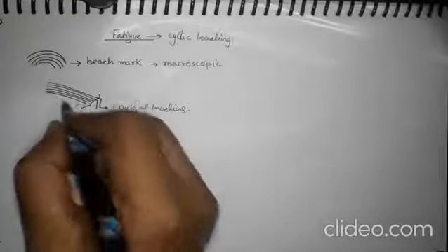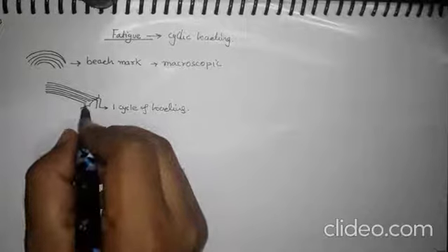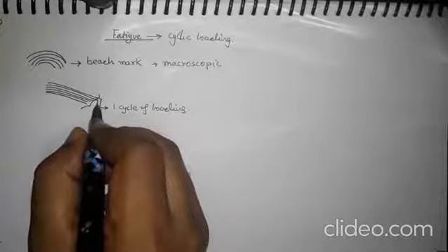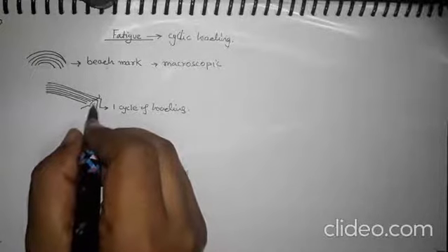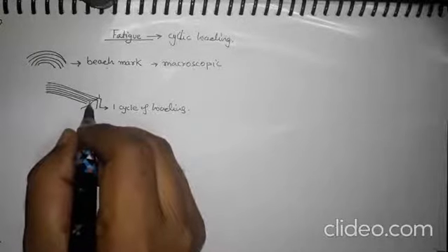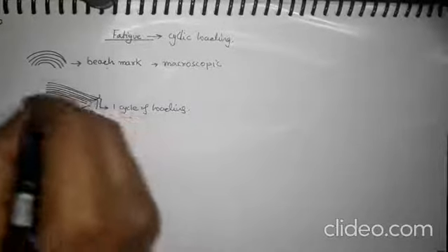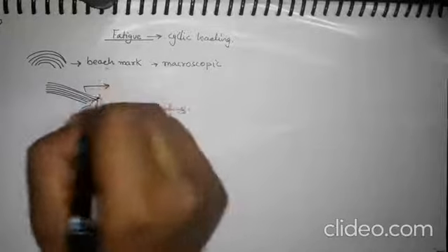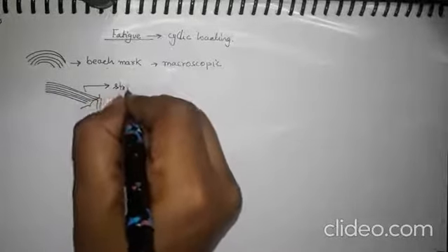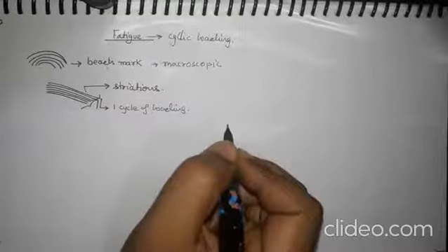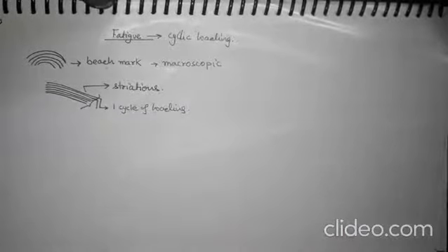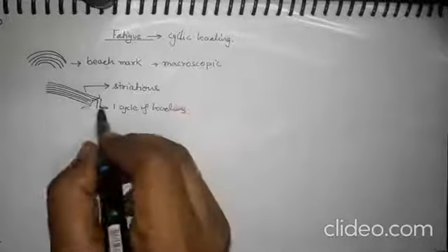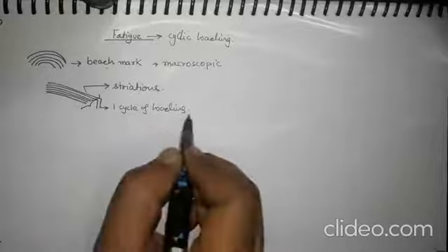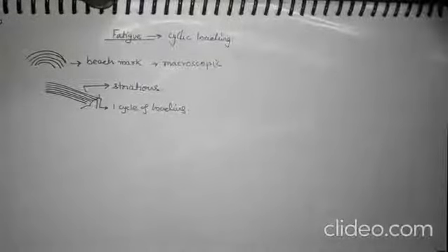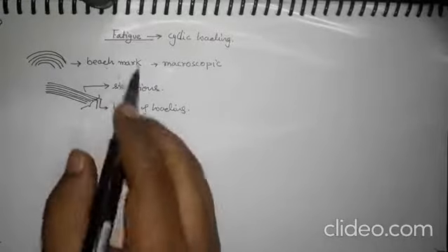This feature which is visible is very small, probably in the range of micrometers, a few microns or something. So these features are different from beach marks because these are microscopic features, and these are called striations. Beach marks are not representative of each cycle. So here these lines do not represent one cycle of loading, but in striations, each line represents one cycle of loading.